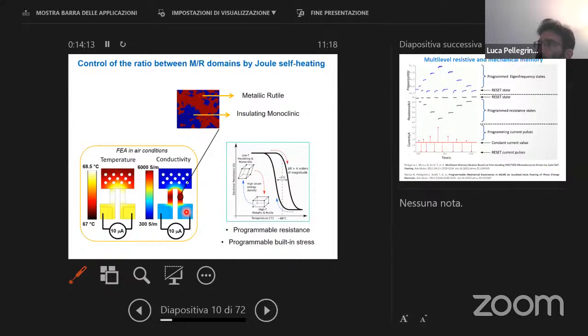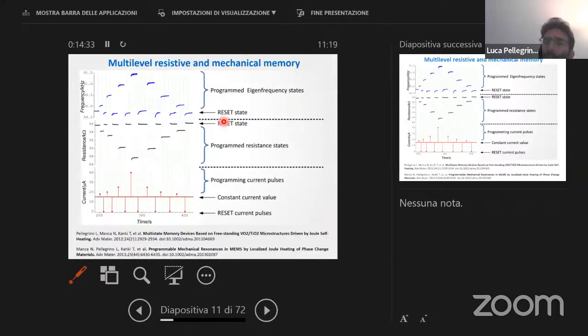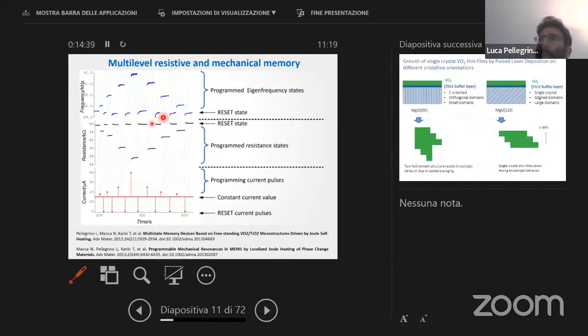Meanwhile, we play with the current and measure the electrical resistance, and we see that we can tune the electrical resistance after current pulses, because we program the ratio between the metallic and insulating state. This works only in this temperature window, because if we cool down the system, we completely erase these regions. So we have both a resistive and a mechanical effect. By changing the number of current pulses, we can program the eigenfrequency. So we have a mechanical memory, or we can program the electrical resistance in a multi-state way.